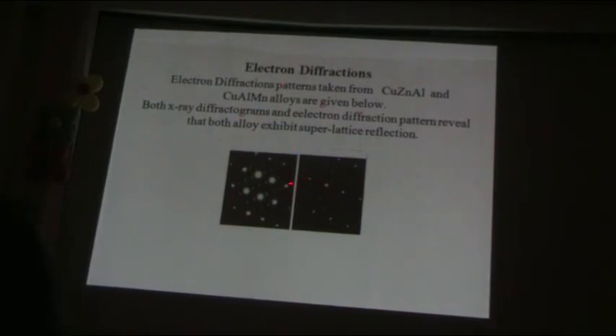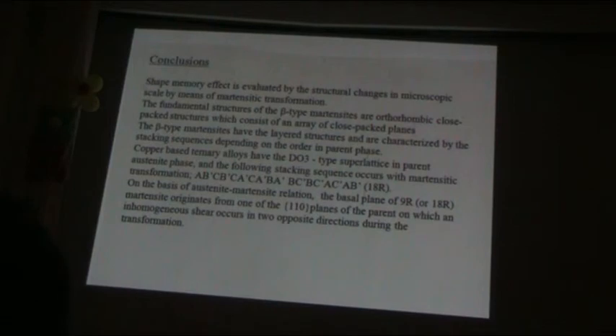Electron diffraction patterns also exhibit the superlattice reflections. On the microscopic scale, by means of martensitic transformation, the fundamental structures of beta-type martensite are orthorhombic close-packed structures, which consist of parallel close-packed planes. The beta-type martensites have layered structures and are characterized by the stacking sequences depending on the order in the parent phase. Copper-based ternary alloys have the superlattice in the parent austenitic phase, and the following stacking sequence occurs with martensitic